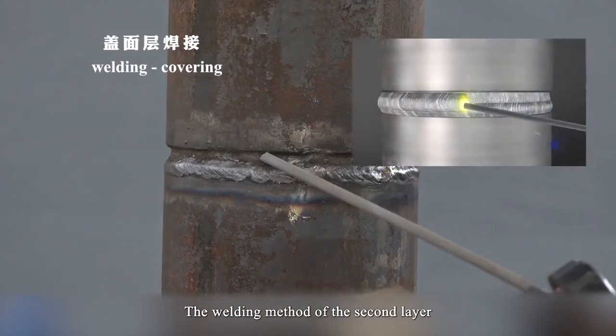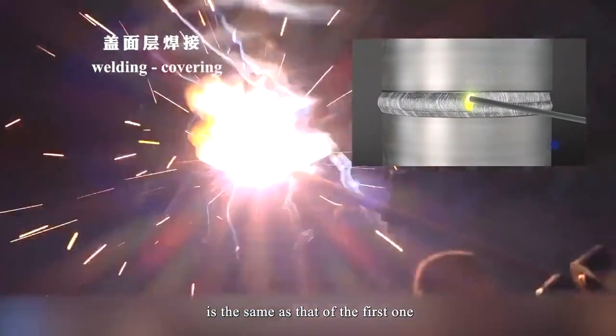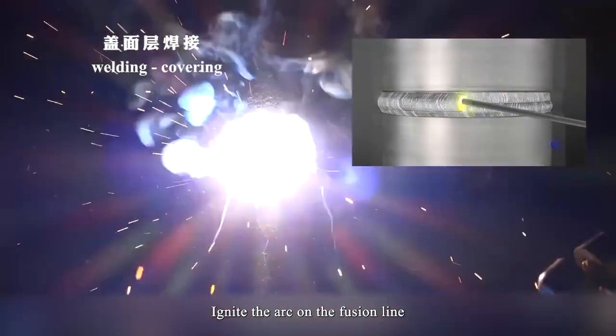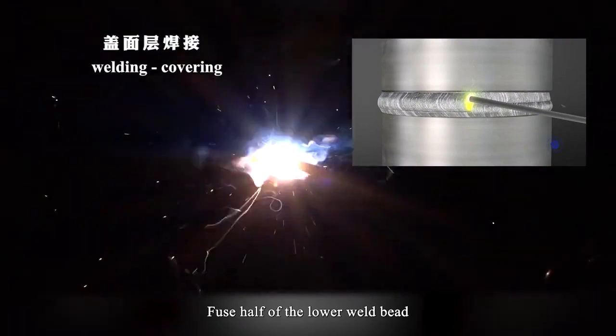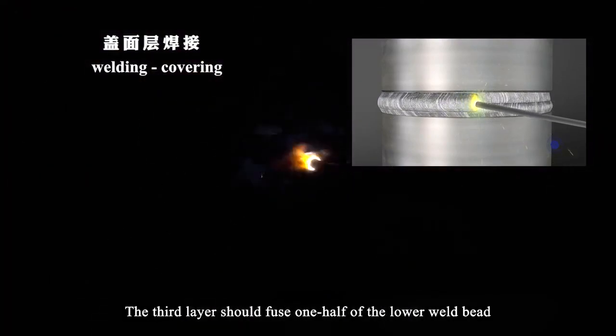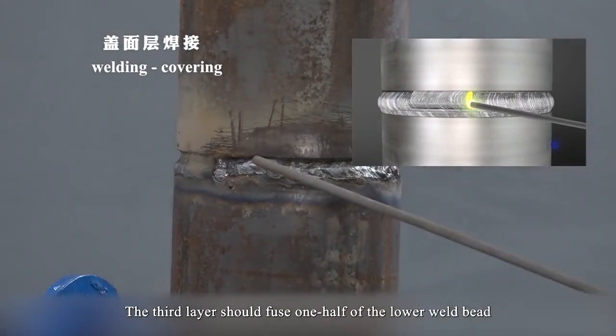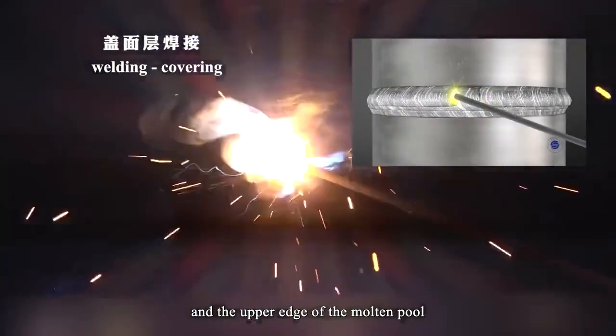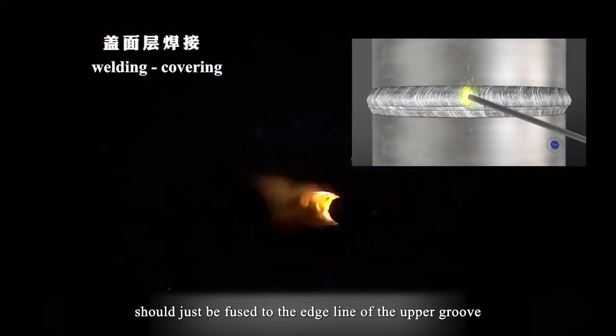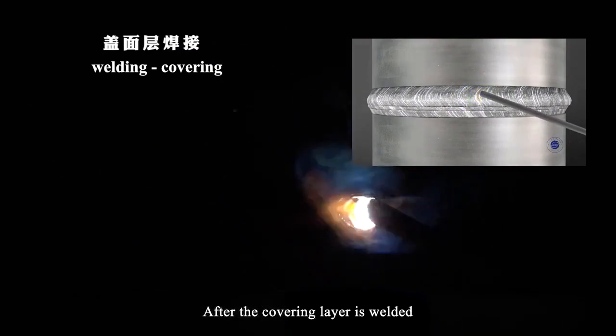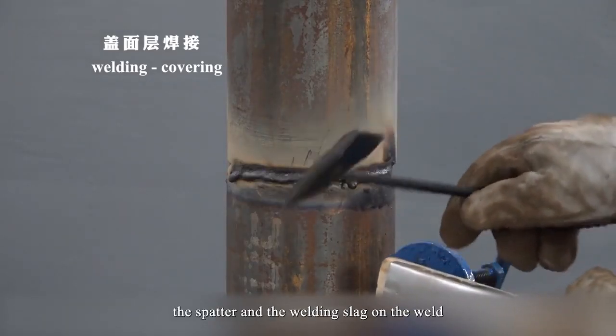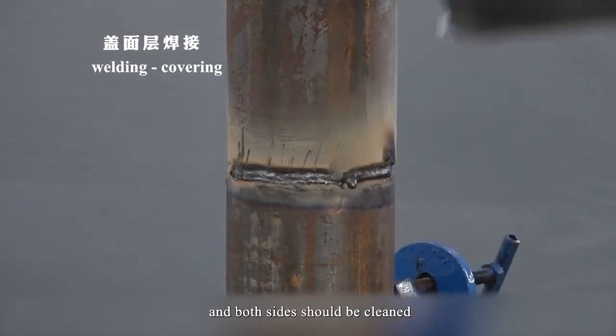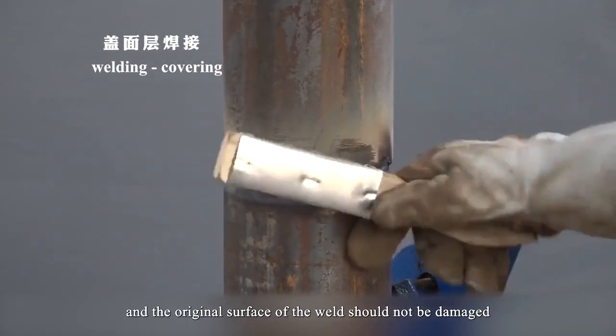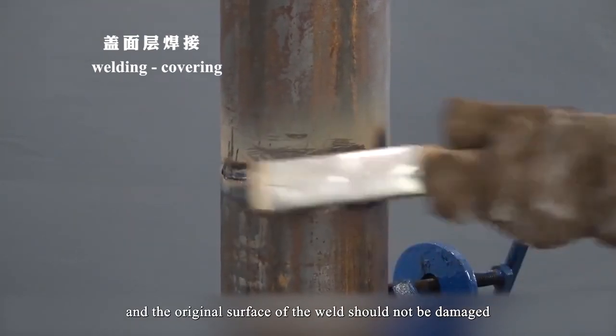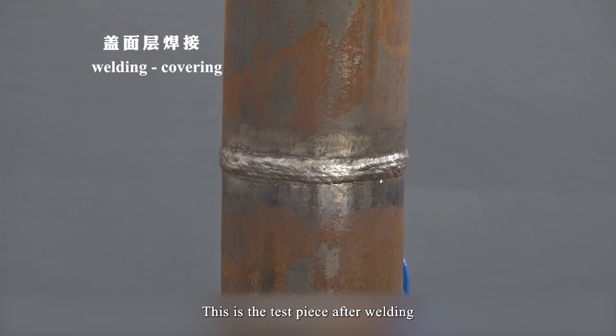The welding method of the second layer is the same as that of the first one. Ignite the arc on the filling line. Fuse half of the previous weld bead. The third layer should fuse 1/2 of the previous weld bead at a constant speed, and the upper edge of the molten pool should just fuse to the edge line of the upper groove. After the covering layer is welded, the spatter and the welding slag on both sides of the weld should be cleaned, and the original surface of the weld should not be damaged. This is the test piece after welding.